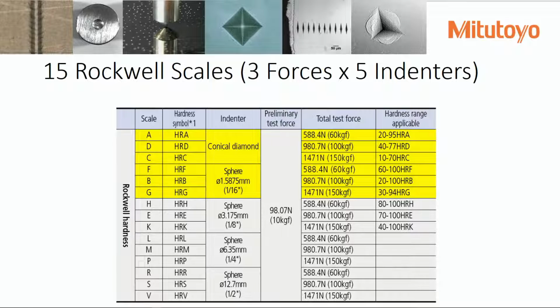So we have 15 Rockwell scales. Again, people get confused, which scale do I want to use? ASTM has a guide, the ISO spec has a guide, but you can pretty much guess that if it's a heat-treated part, it's probably going to be a diamond scale. And if it's a raw material part, it's probably going to be a ball scale.